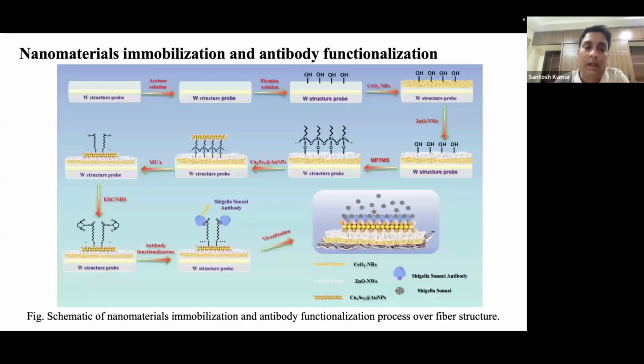So we have fabricated the fiber structure, and after that we go for the nanoparticle immobilization and antibody functionalization. For the nanoparticle immobilization, let us assume that this is the W-shaped optical fiber structure, and we do the coating of nanoparticles. Before that, we do a three-step cleaning process.